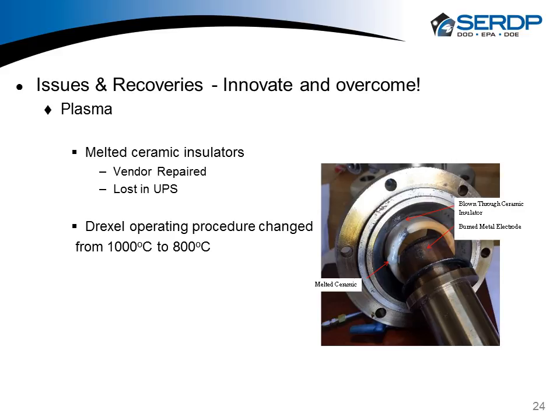Originally, they wanted to run at 1000 C, and then when we showed them this, they said, well, we should probably run at 800 C, because what was going on is we were eventually melting this after a few hours of operation, and the amperage and the voltage started to go out of spec, so we shut down, cooled down, and found that this had occurred. So we had this repaired by Drexel, and I couldn't believe that we lost this thing in UPS. We had to get it remade by Drexel. So this was several months of downtime for us.